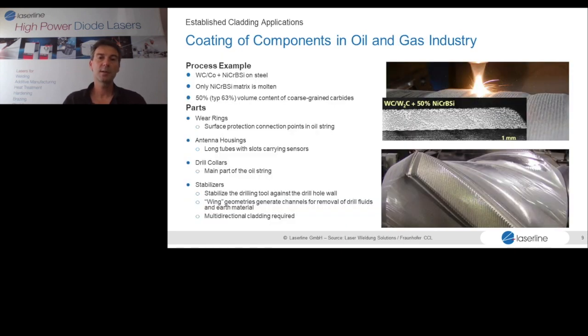This is from oil and gas industry. On the lower right corner, for example, you can see one of the stabilizers that stabilizes the drilling tool in the main oil string that goes down deep for oil drilling and stabilizes this oil string towards the sides. And so this is tungsten carbide clad into the surface for wear protection. Tungsten carbide in typically nickel bases or nickel alloy bases.